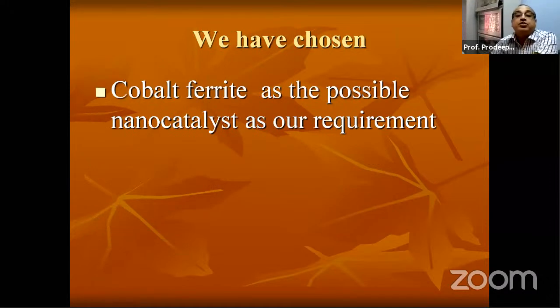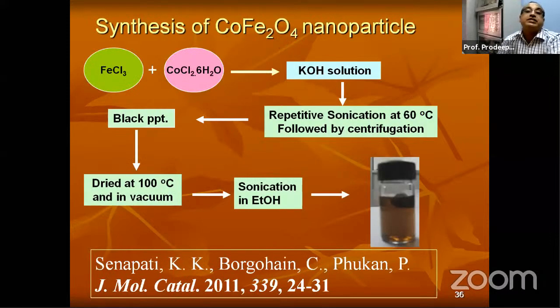So we have chosen cobalt ferrite as a possible nanocatalyst for our requirement. This is the cobalt ferrite synthesis. This is FeCl3 and CoCl2. This is a simple co-precipitation method, like how they also do zeolite or hydroxide. Then in presence of some potassium hydroxide or sodium hydroxide, some basic solution, then repetitive sonication at 60 degrees centigrade, followed by centrifugation.